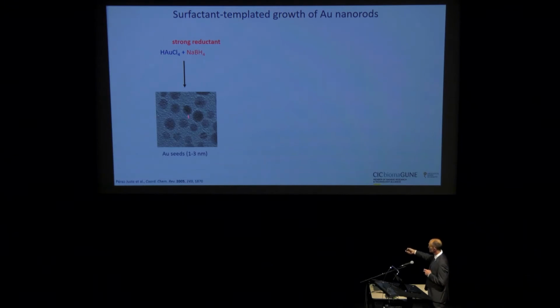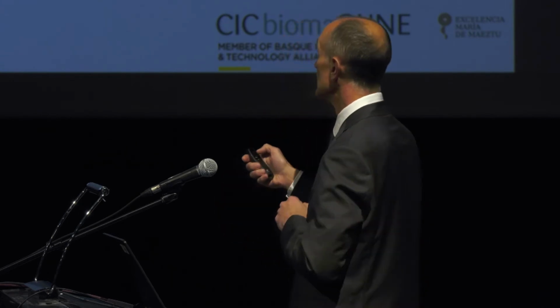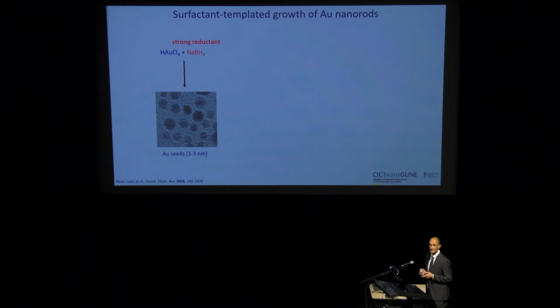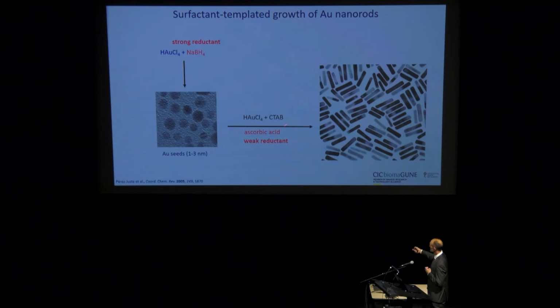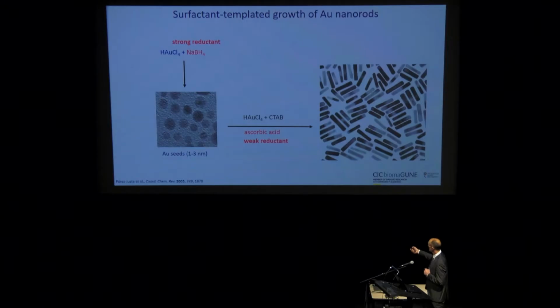gold chloride into gold crystals of very small sizes. And then these crystals are stable for a while. If you leave them for a long time, they will probably ripen and become bigger, which can be used as an advantage, as I will show in a minute. But typically, you use them very quickly after making them. And then what you do is adding more gold chloride in the presence of cationic surfactant, and also in the presence of a weak reducing agent like ascorbic acid, so that now the reduction of gold ions into gold atoms does not create new nuclei. They only grow on the existing seeds.